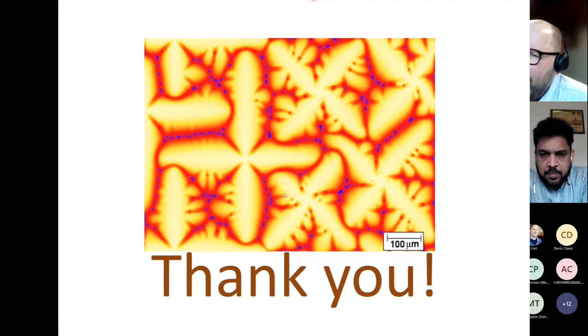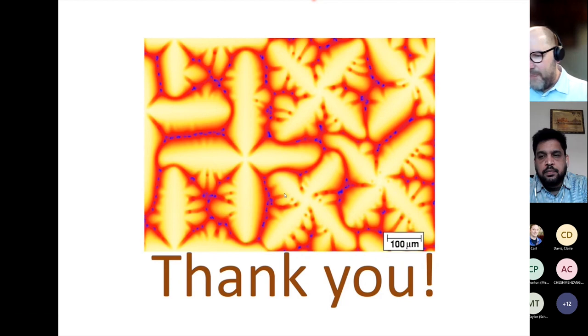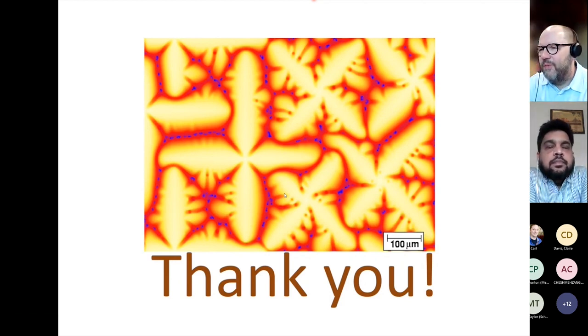I think a lot of that depends on which approach you're looking at to some extent. There's no simple answer to that question. If you do the classical approach where you do the parallel tangents, some of them might not have as much effect as you would think. In other cases, with the approach I presented towards the end, the chemical potentials will include those effects. They will also include the effect if you have a pileup of an element at the interface: it will slow down the interface and lead to something like solute drag, because it will affect the chemical potential and the temperature gradients. It will affect some elements more than others, and those cross terms are in there, but they're coming out of the thermodynamics and potentially the mobility coefficients as well.